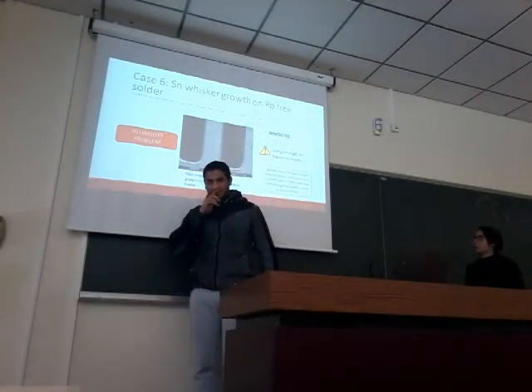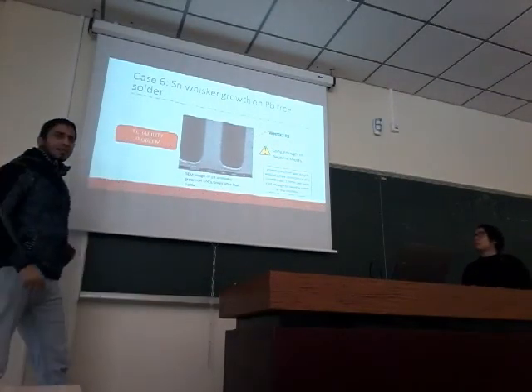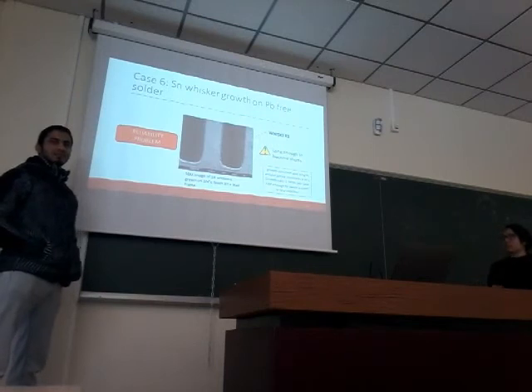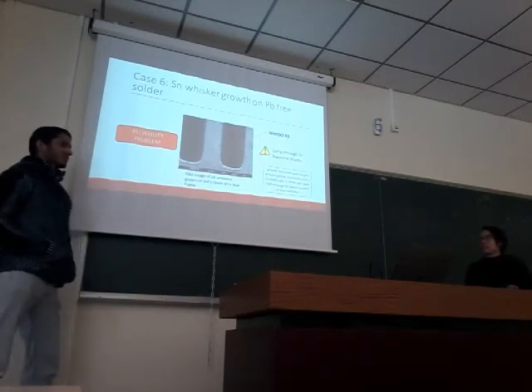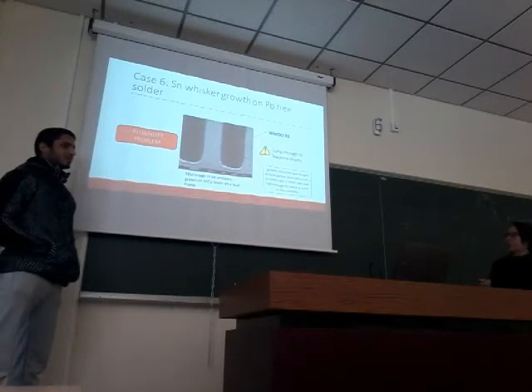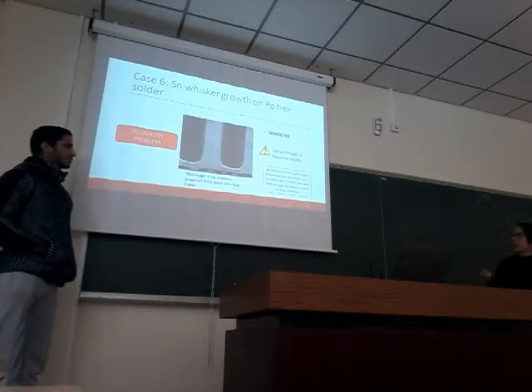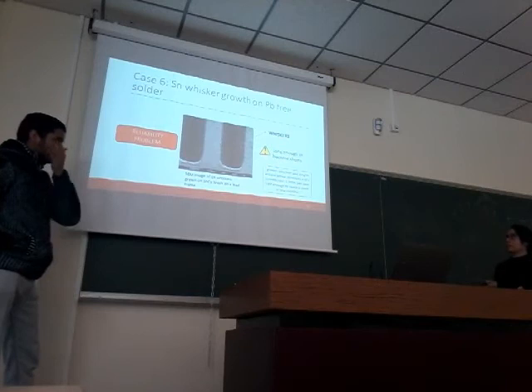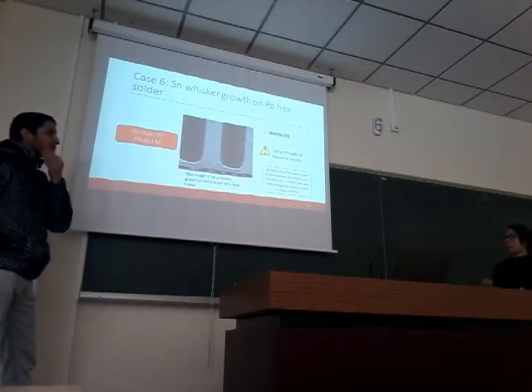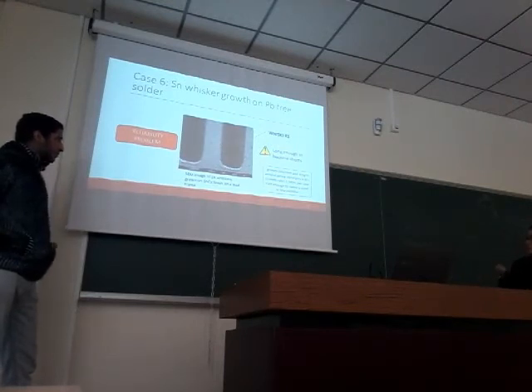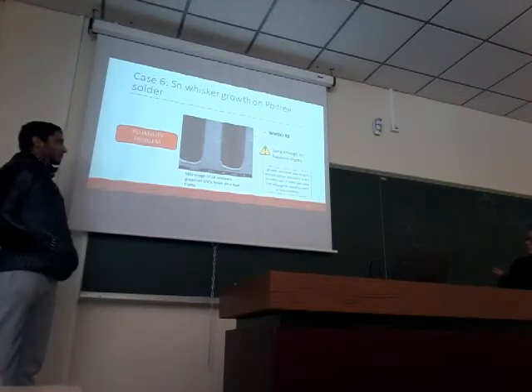Okay, so I will talk about the whiskers, the tin whiskers that grow on lead-free solder. What happens is that, for instance, here we have a lead frame for surface mount technology, and when we replace the lead with another substrate like tin copper, we get the formation of whiskers. Like this, we can see here.